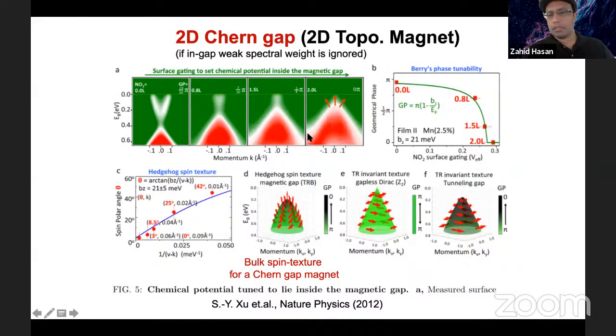And so all these tests, for example, if it's a time-reversal invariant texture, meaning a non-magnetic Dirac fermion, or even a time-reversal invariant texture with a tunneling gap, this would be its signature: there is no polarization of the surface Fermi surface if you tune the Fermi level there. Whereas if you tune the Fermi level here, your surface Fermi surface will be spin polarized. So these systematics allowed us to identify experimentally a topological gap, a Chern gap, in a magnet.